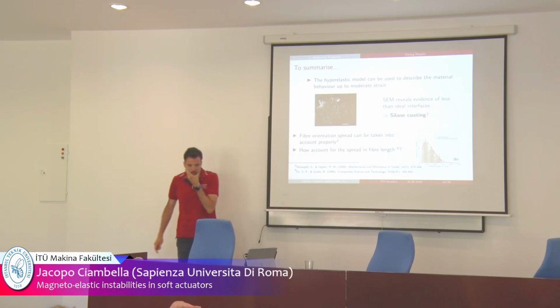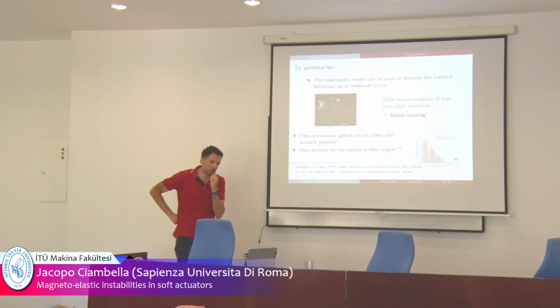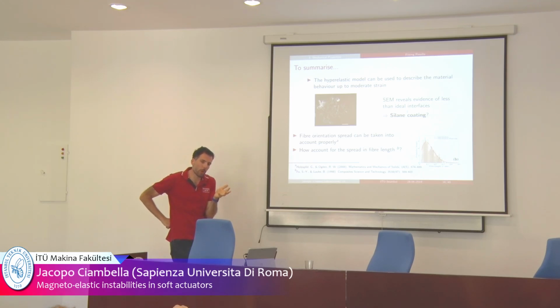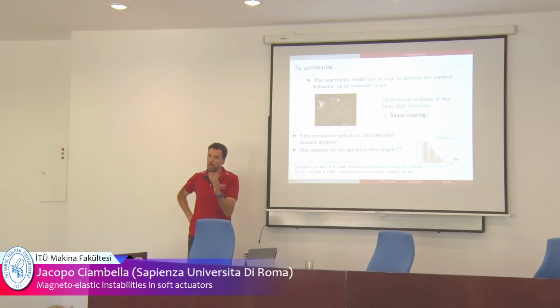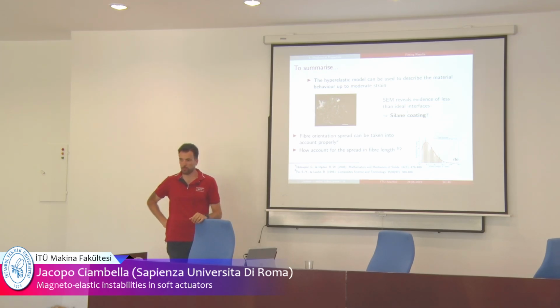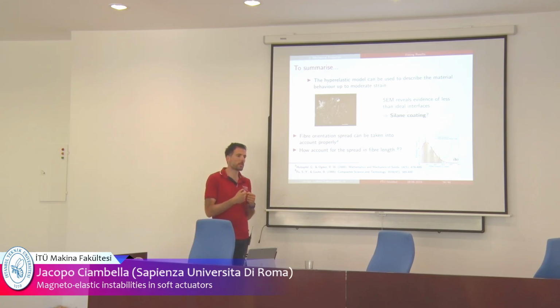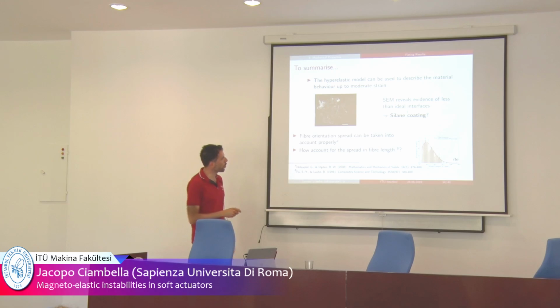So the conclusion of this part, the hyperelastic model can be used quite well. We saw some divergence between the model and the experimental results. We think that this is due to the fact that the interaction between the fiber and the matrix is not very good. So for strain higher than 30%, you will have detachment of the fiber from the matrix. So the mechanical properties are lower than expected in that case. And what you can do to solve this problem is silane coating.